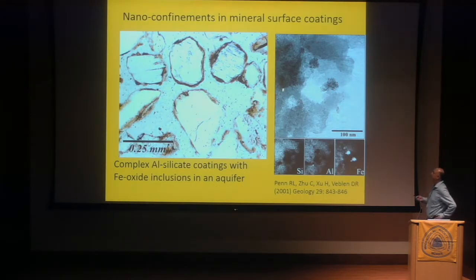Okay, so where do we find nano-confinements in the environment? This is a paper from Penn from 2001, and she showed here coatings on quartz grains, and they appear all brownish. One would think, oh, they're all composed of iron hydroxide, but they're actually complex aluminum silicate coatings with iron oxide inclusion shown here. And we have here, as you can imagine, quite a significant amount of confined pore spaces.